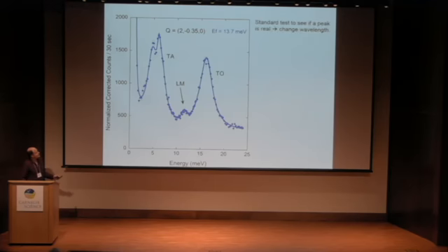you can perform a very standard test to see if a peak is real. All you do is change the wavelength, in this case, the fixed final energy EF. Okay, and we did that. We made a small change. You can see that there is a small change in the optic mode intensity. It actually has a slightly larger integrated intensity, but not much, just a few tenths of a percent. It gets a little broader and a little bit weaker here, and that's expected because your resolution volume is larger.